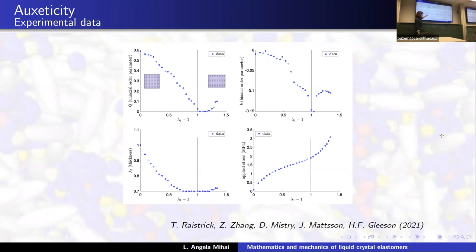And this is the thickness that we are talking about. It decreases to begin with, then stops decreasing, and then starts to even increase. And this is the applied stress. You can see this rubbery S shape that people who study rubber are quite familiar with. This S shape for rubber tells us that Neo-Hookean is not going to capture it, not even Mooney-Rivlin. So we will attempt an Ogden-like model,